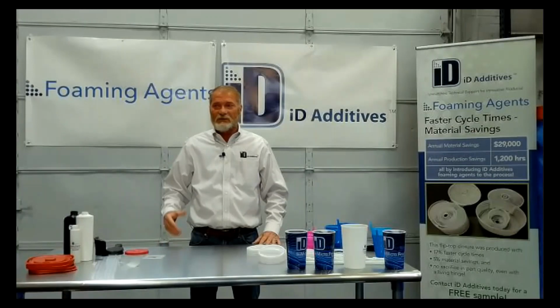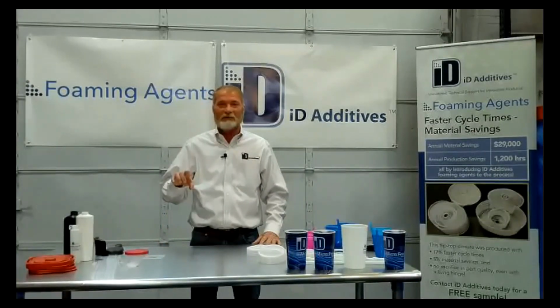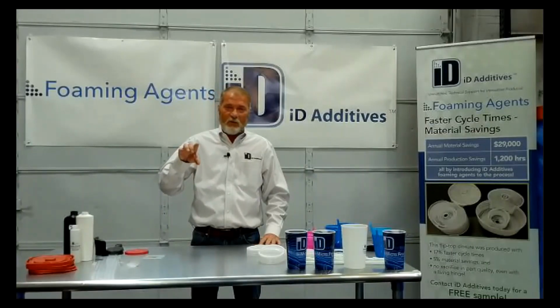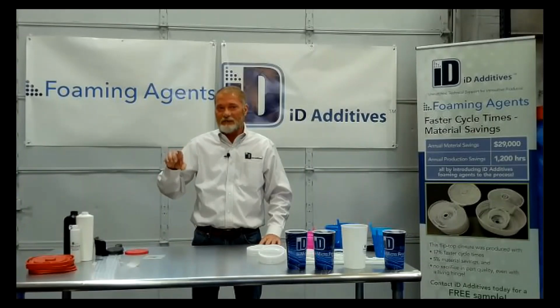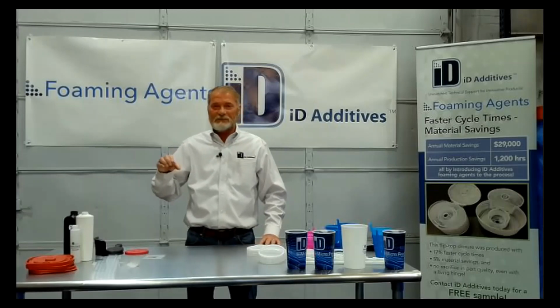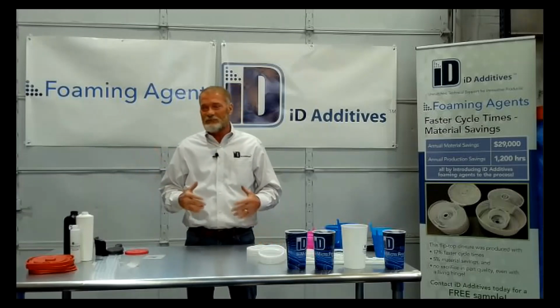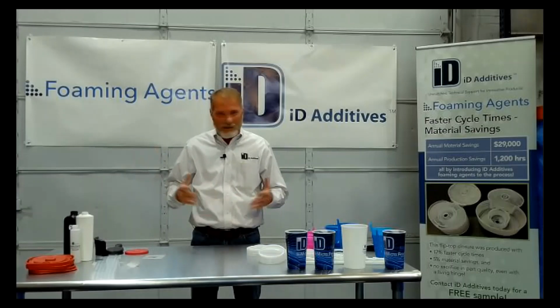So if you don't have a shut-off nozzle, it doesn't mean that it won't work. It just means you're going to have to bring that nozzle temperature quite a ways down. And remember, that nozzle just keeps the heat. It's not really supposed to heat up the material. It's supposed to maintain the material.